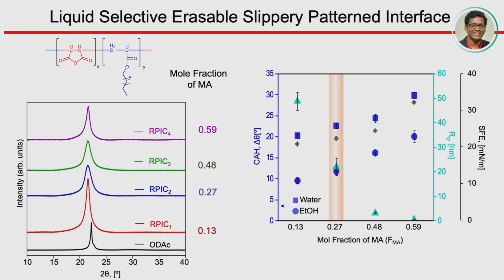anhydride. Okay, so our expectation is that when you are decreasing this roughness, the slippery property will be better, but in reality it is not happening. Why? Because if you see, there is another axis, that is for surface free energy, that is increasing. Okay, when you go for more maleic anhydride, this is a more polar group, right? The surface free energy will be increased, and because of that you will see this interface becomes slippery to only water, not for the low surface tension liquids.